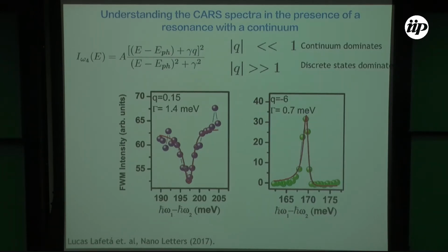So we use this kind of equation to fit our data, and you can see that the Q value for graphene is smaller than 1, and the Q value for boron nitride is much larger than 1, okay? So it makes sense, right? In graphene, you have a very strong contribution from the continuum electronic states that are available, but in the case of boron nitride, you don't have this contribution from the continuum states. You just have the contribution coming from the discrete phonon states. Okay.